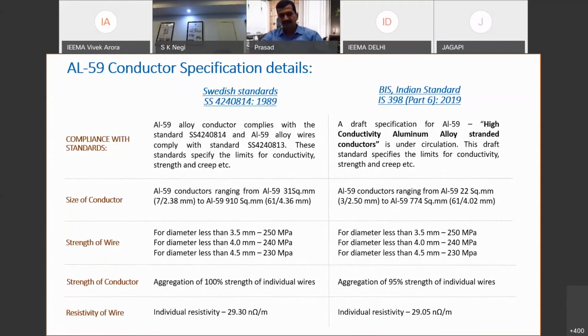But the important factor which we can look at, when we are calculating the overall UTS of the conductors, is that the Swedish standard allows 100% strength of the individual wire, which can be aggregated to arrive at the breaking load of the conductor. Whereas in the Indian standard, we are having 95% of the individual strength of the wires. At the same time,